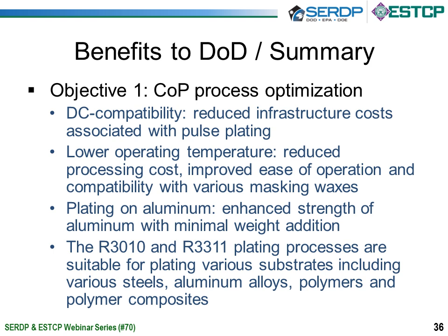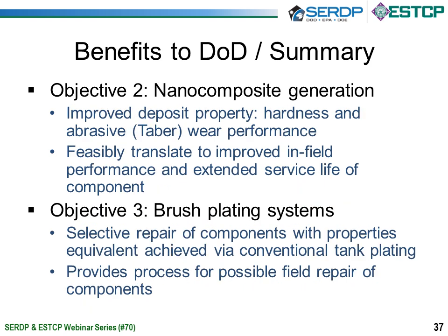The plating on aluminum can enhance the strength of aluminum with minimal weight addition. And both the R3010, which is the conventional cobalt phosphorus, and the 3311, which is the process modified for aluminum, are suitable for plating a number of substrates, including steels, polymers, and polymer composites, if you want to extend the technology to new applications. Related to Objective 2, the composite generation improves performance of the coatings, both in terms of hardness and Taber wear, ultimately hopefully resulting in improved field performance and extended life of components. And the extension of the technology to brush plating systems allows it to be used for possible field repair of components, so less costly.